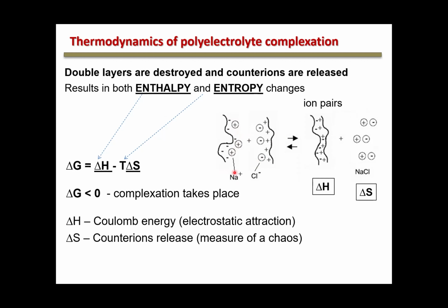And when two oppositely charged polymers interact with each other in the presence of salt, they form a polymer complex, which is called in this case every plus and minus would form an ion pair. So this is a polymer complex, and counterions are now released. Before they were bound to the polymer backbone, now they are released. And release of counterions drives the entropic component in this physicochemical thermodynamics and interaction between the polymers.